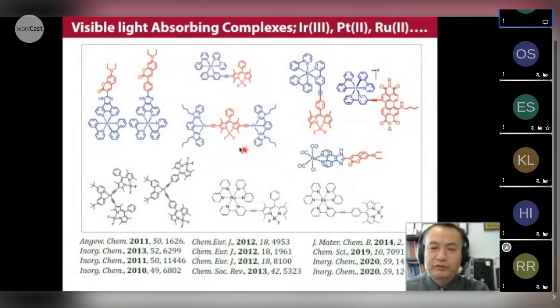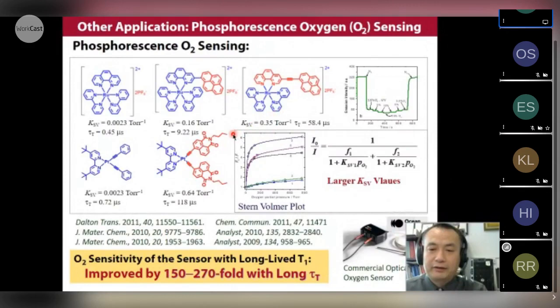So we prepared some different complexes. All these complexes show a very strong absorption of visible light because they contain organic chromophore, coumarin or BODIPY. All these chromophores give strong absorption of visible light. We also observed long triplet lifetime for these complexes. The application of these complexes is not limited to TTA upconversion.